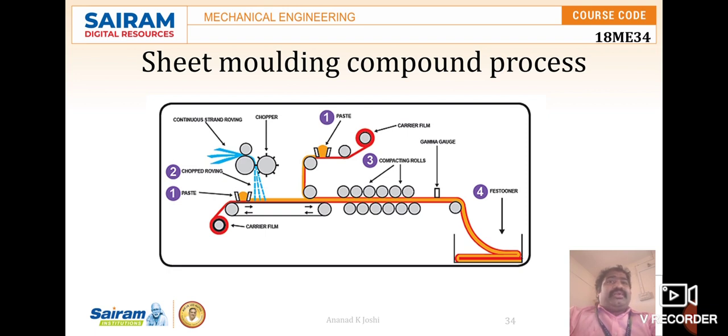They are then placed on a take up roll while the material matures, which occurs in an oven type controlled area for at least 48 hours. It is then placed into a cooling area where it is solidified, and once it reaches this cooling area it must be used within 30 days. The sheet molded rolls thus produced serve as a raw material to make a composite material by another process.